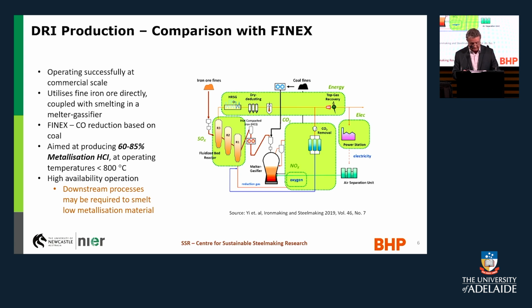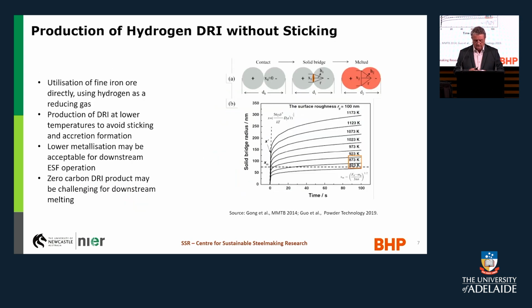So POSCO's Finex process is a good comparison to make with the Finmet plant. But I think the Finex plant and certainly the Hyrex have perhaps set their targets a little bit lower in terms of running a lower metallisation, which avoids many of those sticking problems that we'll face with the Finmet plant. This one here is a little bit about some of those things that happen with hydrogen reduction of iron ores. So to do it without sticking is the challenge, and I've seen a lot of that emphasis in the posters that I've seen at lunchtime. So a lot of people are thinking about that problem. But no doubt that lower temperature, lower metallisation is certainly going to be something that helps in that mission to avoid the sticking.